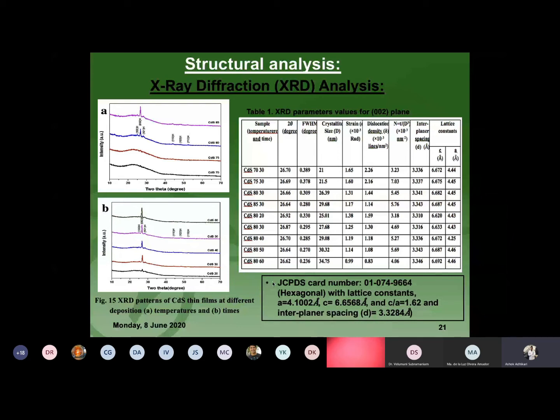We also calculated other parameters, interplanar spacing and lattice constant, with the interplanar spacing obtained through Bragg's law. The obtained lattice constant resembles the hexagonal structure of the Joint Committee Powder Diffraction System, JCPDS card number 01-0749664.